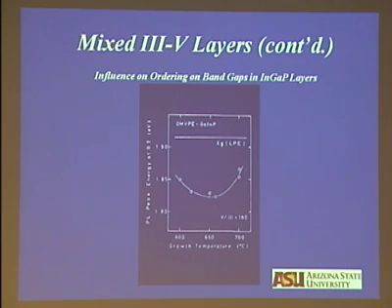So atomic ordering lowers the band gap of the material. There is a story: Philips used to make these lasers for disc players, and they did not understand the growth. The band gap is very sensitive to atomic ordering, so they used to get fluctuations in the lasers they were developing. Finally, they went away from the exact orientation and killed atomic ordering, and they were able to produce lasers with a consistent wavelength.